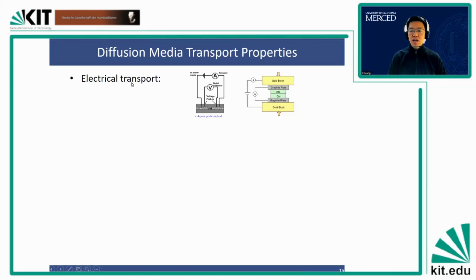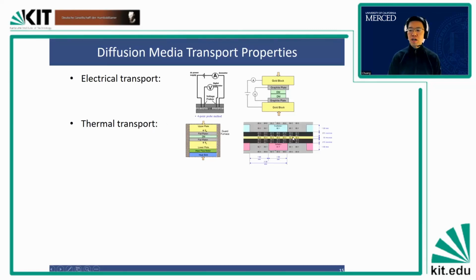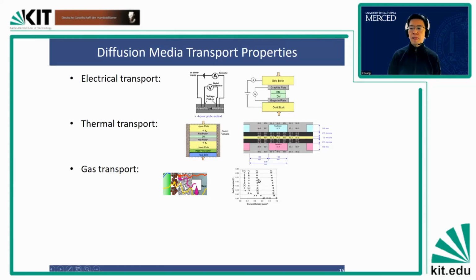One of them is to study electrical transport, both in-plane and through-plane. And then thermal transport, again, both in-plane and through-plane thermal transport. We were able to also put together a thermal transport model to predict temperature within a fuel cell. We also developed tools to characterize gas transport, for hydrogen transport and oxygen transport. And there was a tool called limiting current that I will introduce a little bit later, a diagnostic tool to characterize the features of hydrogen and oxygen transport within a fuel cell.